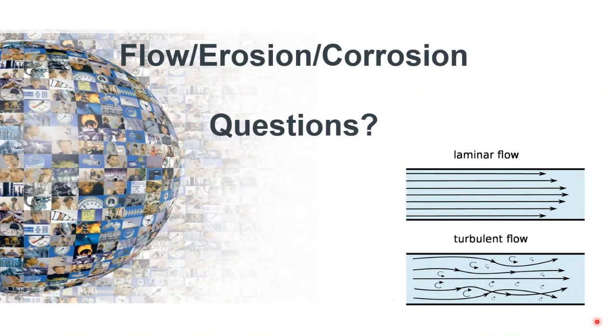Phil, do you have anything you'd like to add to that? Yeah, sure. Thanks, Hassan. So great question there. That is a common question that we receive. But when you look at tubing itself, tubing is actually annealed and a much softer material. So when you bend tubing, what you're actually doing is work hardening and reversing that annealing process, and it actually becomes the strongest part of the system. So like Hassan said, if we did take a tubing system and overpressurized it all the way up to that burst pressure, you actually would see a tubing system would fail in the longest straight section, and those tubing sections that are bent on the sweeping bends, those would actually be the strongest sections and would remain untouched.